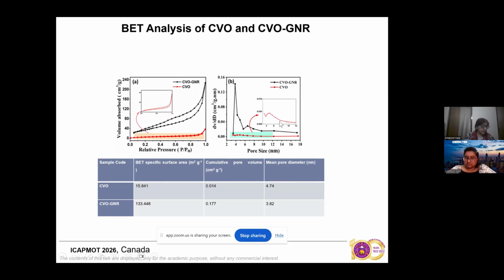To get uniform pores for the intercalation of the zinc, we need a uniform porous structure. So BET analysis really helped us to see whether our material is suitable to make a cathode or not. We can conclude that CVO depicts a typical type 3 adsorption-desorption isotherm, indicating weak surface interaction. In contrast, you see that CVO GNR shows a little bit of hysteresis also.